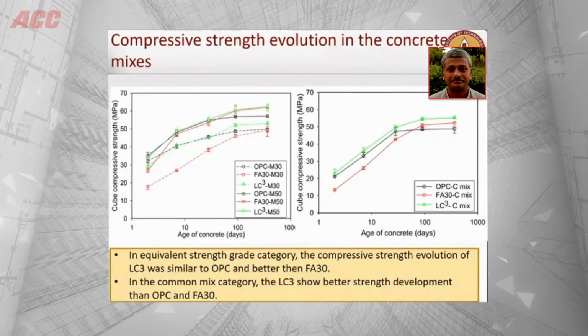So let's first look at strength. If you look at the cube compressive strength for the M30 mixes, which are here, this is 1 year data, mind you. At 28 days, all of them achieved the M30 characteristic, but you can see very clearly that the fly ash based system had a lower strength gain rate. But by 1 year, all of the cements are at the same level. So there's not much difference.